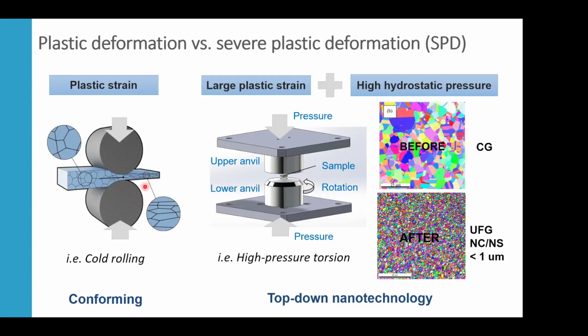And grain refinement is of course accompanied by the reduction in the macroscopic shape of the workpiece. But also the accumulation of dislocations and defects will increase the amount of strain, and then this will eventually lead to sample failure if we do excessive plastic deformation. But if we increase the pressure in a hydrostatic way with large plastic strain, then we can apply much more deformation to samples. So probably the most famous SPD, severe plastic deformation process, is high pressure torsion, as you can see in the image on the right.